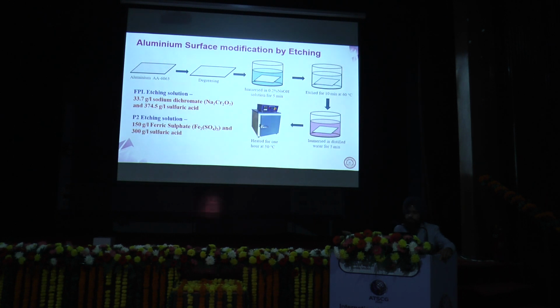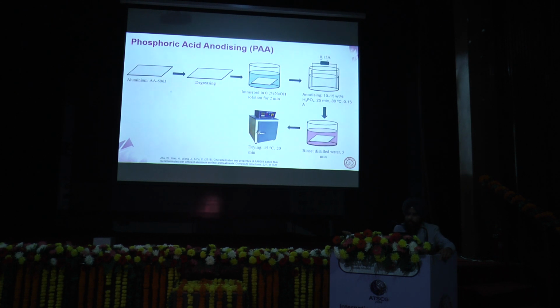We used three types of surface modifications in this study. First is etching, and we used two different types of etching. FPL etch, that is Forest Products Laboratory, using sodium dichromate and sulfuric acid. Second one is P2 etch, using ferric sulfate and sulfuric acid. For the alkaline treatment, we etched and then immersed in distilled water and heated for some time. We also used anodizing on our aluminum face sheets. The process is very simple. After degreasing and alkaline etching, we immersed in 0.2% NaOH, and then specimens were anodized in phosphoric acid at 30 degrees Celsius, followed by rinsing and drying.